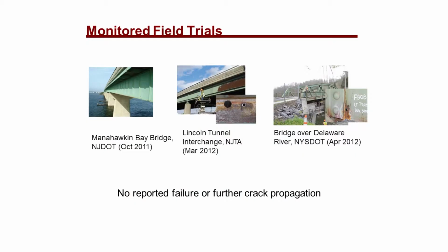We have FEA, and then we have lab testing, and then it was time to do some field trials. So we did 3 monitored field trials, 2011 and 2012, in 3 different environments to try to give us some good ideas of what it would look like. So we had the Manahawkin Bay Bridge in New Jersey that was done in a sort of littoral environment. For heavy loads, we had the Lincoln Tunnel Interchange. That's also where the weld seam test was done.